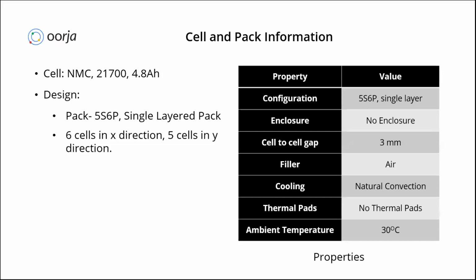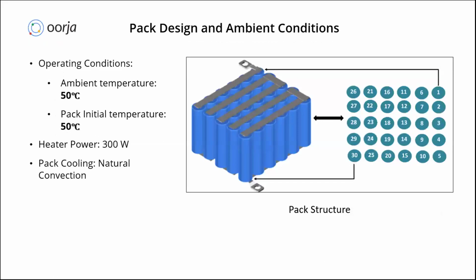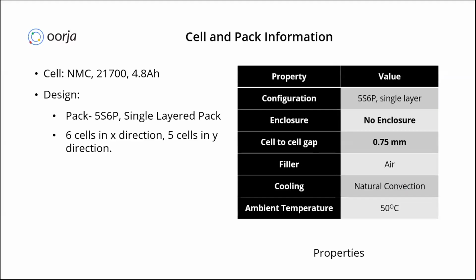So by using this product, we have created one small case study wherein we use this NMC 21700 4.8 ampere hour cell itself. The configuration is very simple. That is a 5S 6P single layer pack, constructed without any enclosure, wherein the cell to cell gap was considered as 3 mm in the initial case.